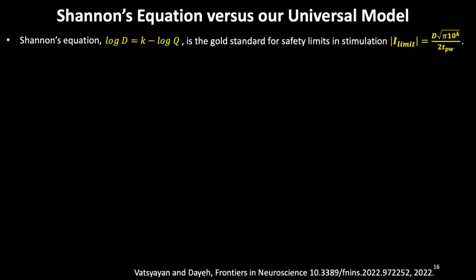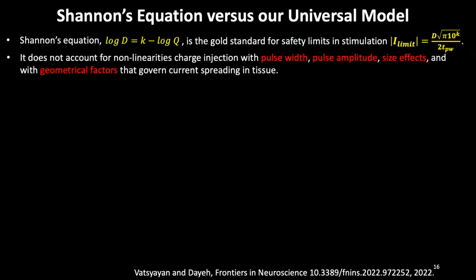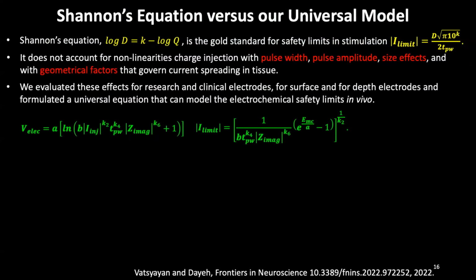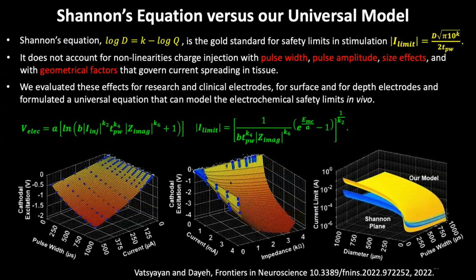Now, the gold standard for deriving the safe currents in electrical stimulation clinically and in research is the Shannon's equation, which relates the charge density to the charge per phase by an empirical formula. And that formula doesn't account for nonlinearities for current spreading, nonlinearities with area, nonlinearities with the pulse width. So here we did a study both in benchtop and in vivo to be able to estimate the voltage drop across the electrode tissue interface, and then calculate the safe currents that we can inject into the tissue without causing